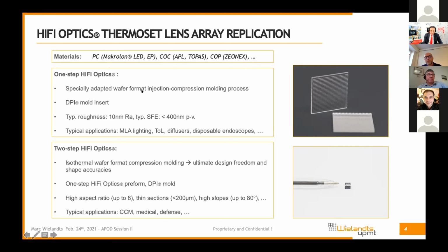The 1-step process is a wafer format injection compression process, and it allows us to mold wafers to a size of diameter 150 maximum. And so we have a number of structures inside that wafer that are then later diced or after the coating. And again, the roughnesses are low, and the SFE is a little bit higher in this process, but this process is extremely efficient, with low cycle time. So we have built a standardized tooling setup where only the structures are modified,